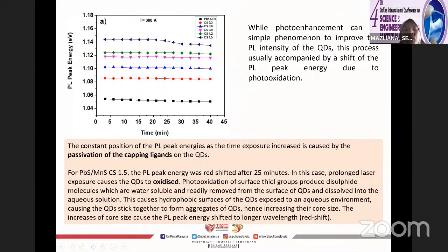So we tried for the other samples and we monitor in terms of the PL peak energy. Here when we increase the time, start from 0 until 40 minutes, we can see that for all samples, the PL peak energy is constant. However, for the sample with the thicker shell, 1.5, we can see that there is oxidation, photooxidation. That's why we can see there is a shift in the photoluminescence.